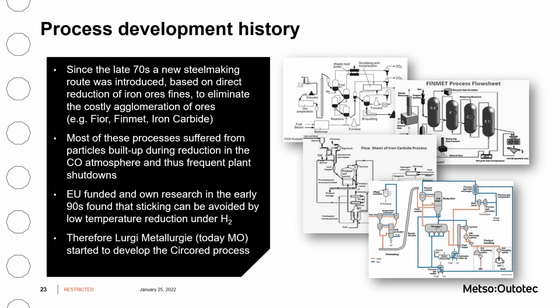From a historical perspective, hydrogen was an enabler for the direct reduction in fluid bed reactors. As early as in the 70s, direct reduction in the fluid bed was introduced, but suffered from problems with particle sticking, material buildup, and frequent shutdowns caused by the high temperatures needed for reduction under carbon monoxide. Own research in the 90s revealed a healing effect when running the reduction on hydrogen, as the temperature could be decreased to avoid sticking. This was the starting point for the Circored process development.